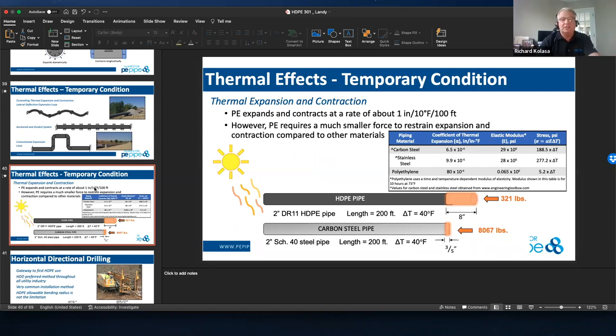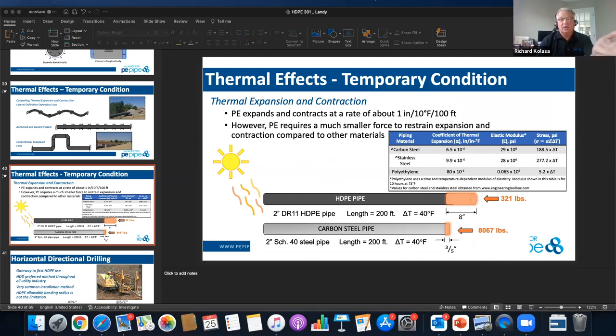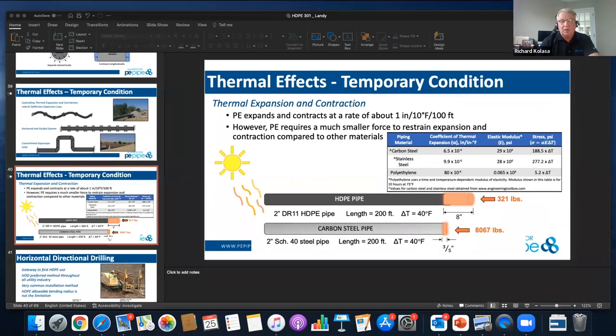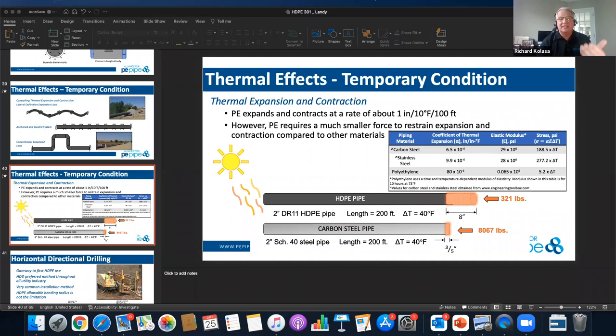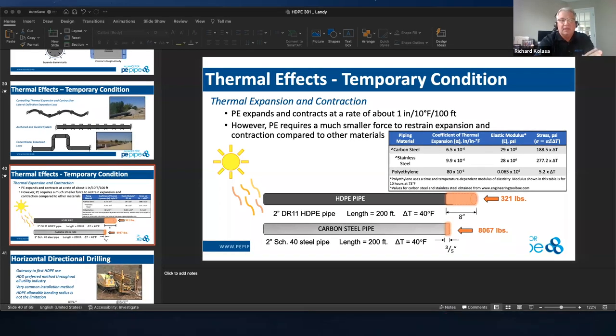In this slide, you can see in a comparable situation, carbon steel to high density, the loads and the stresses that are applied when that expansion and contraction occurs. You can see they're significantly less in polyethylene, so we can manage that easier. For the above ground questions, if you want to run a line above ground, your ambient temperatures are going to change throughout the day. So 1 inch per 10 degrees per 100 feet of pipe applies to any diameter as long as it's completely unrestrained. Any kind of friction on that pipe will reduce that value. However, this is the worst case scenario, so you can button it up.